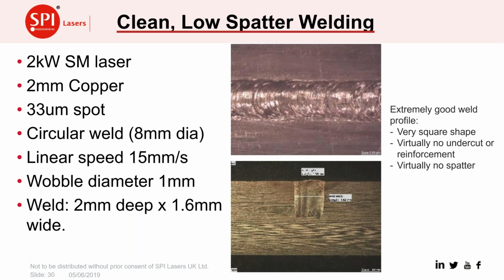And just to show you also the low spatter effect. Here we're running at not a particularly fast linear speed, but we're producing a nice 1 millimeter wide weld with a very uniform cross section, almost a square bottom there, but it's 2 millimeters deep and 1.6 millimeters wide. This is part of a large circle that we were welding on the surface of the copper. It looks a good weld profile, and that comes from getting the right recipe for the weld in terms of the overlap, the linear speed and the frequency of the weld.